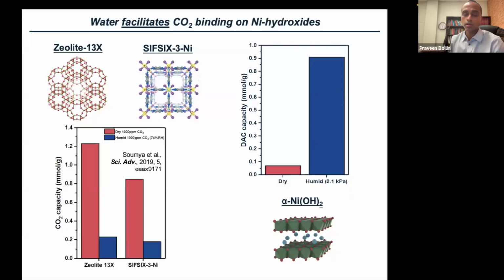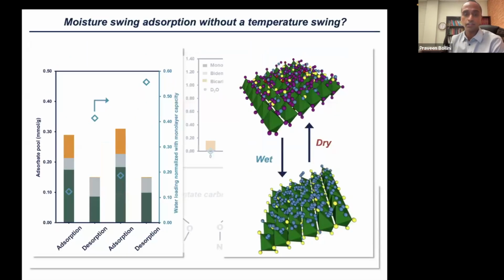So you can have a humid airstream or any general carbon capture stream, any stream that you would want to capture carbon from, and without any pre-treatment of the gas, you could expose it to your sorbent and capture CO2. In fact, again, in the interest of time, I won't go into too much of the detail here, but you can basically capture carbon dioxide without any cycling of temperature at all.